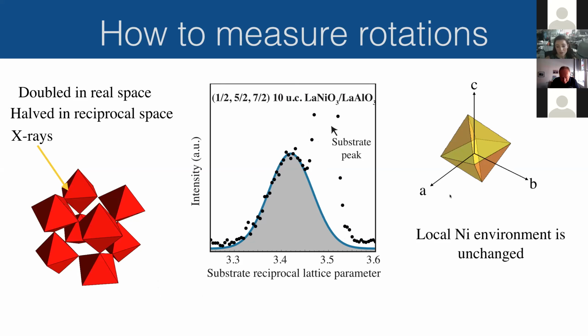Basically the result is that if the rotations are dominating, so the octahedron is rotating much more than it's changing its bond lengths to accommodate the strain, then what is most likely happening is that the nickel that sits inside this octahedron doesn't really feel any change at all. The local coordination with the oxygen is basically not changed. And this is what you need to change in order to have this orbital polarization. So rotations are probably detrimental to the goal of orbital polarization.